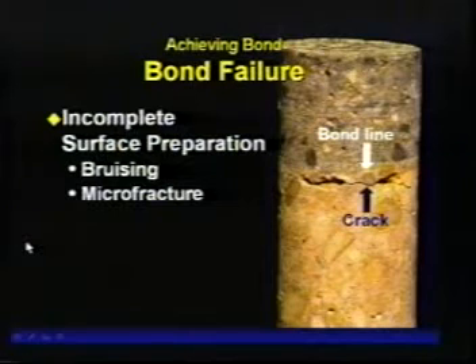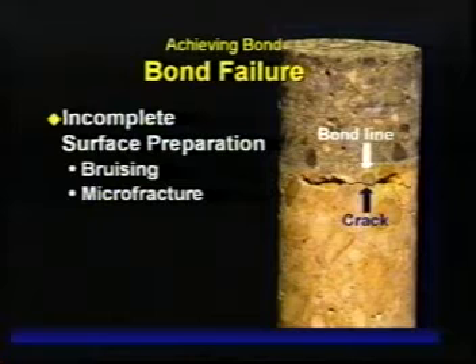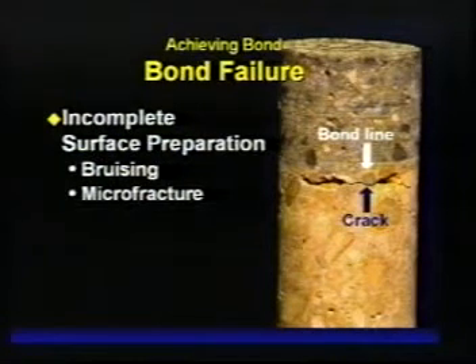One of the important things that we've learned, and is referenced in these documents, is the effect of improper surface preparation can actually cause a bruising. And if the bruising is not removed, number one, if you use the right equipment, you can minimize the bruising. But if bruising is occurring, it's very important to remove it, because this will become a bond breaker. Actually, a very weak bond will occur because of that. And this is just some examples of the microfractures that bruising will cause.